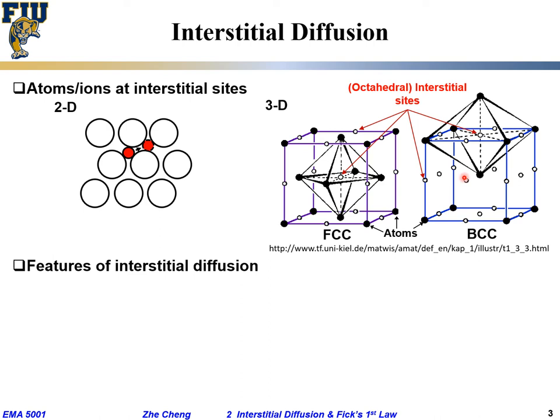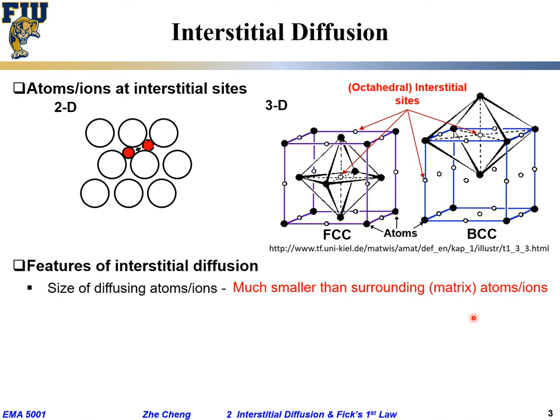Okay, and the feature for such so-called interstitial diffusion would be that the size of the diffusing atom, or the solute atom, is much smaller than the host or the matrix material. Much smaller, typically. How much smaller? Two examples. One is carbon diffusion in iron. The carbon has an element atom size of only 70 picometer, 0.7 angstrom. This guy, iron, is 140 picometer, or 1.4 angstrom, or 0.14 nanometer. So it's roughly half the size.